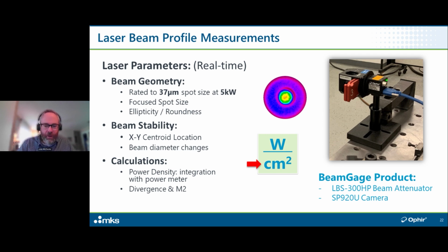The BeamGage, an Ophir product, consists of an attenuation device that reads up to 5 kilowatts of laser power and reduces it down to nanowatts to view beam sizes down to about 37 microns in diameter. It does view the focus spot size. It does view the ellipticity, the roundness. This image, with the blue, orange and yellow, is what you can typically see from a BeamGage system. It also gives you the beam stability.